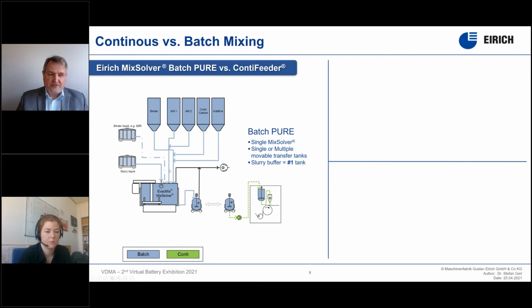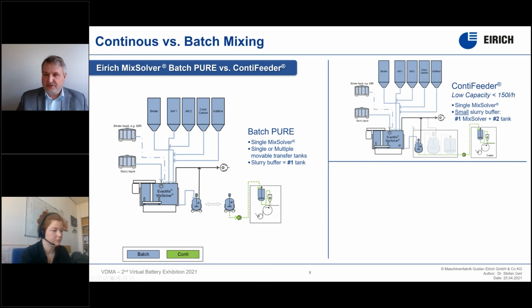In the pure batch process, we are weighing out, we are mixing, then we are transferring it into a storage tank, we are doing the degassing inside of the mixer and the storage tank, and then the tank is moved to the coating line next door, connected, and then the discharging of this slurry tank to the coater takes place. With a continuous feeder process, we can do it exactly the same. For low capacities, we only need one tank, because we can then refill the tank. We can discharge from the tank with a perfectly degassed slurry to the coating line.